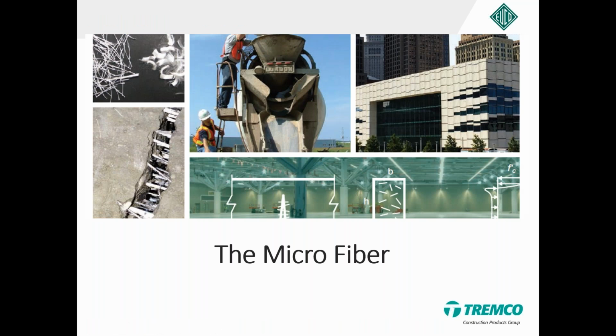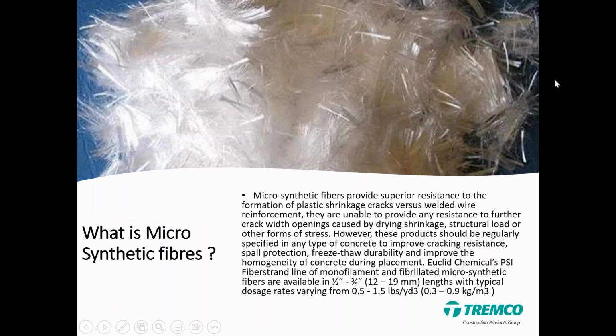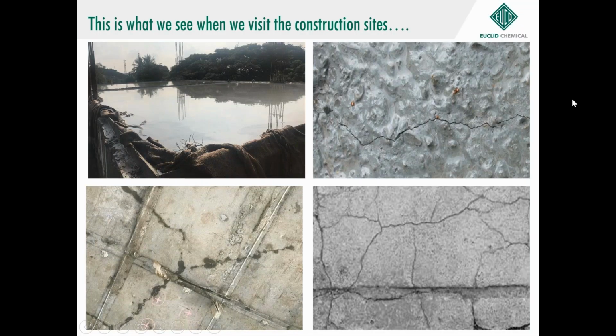So this is what microfibers are. I'll just touch on microfibers. As I said earlier, macrofibers are 51 mm, microfibers are 10 mm, and the 10 mm is used only at 900 grams per cubic meter, only for taking care of the drying shrinkage of the concrete. Please do not use this fiber for any structural replacement at any cost. Definitely, it has a great advantage against plastic shrinkage. Generally, when you go to a construction site, we see this very often. This is something you can take care of by using microfibers.